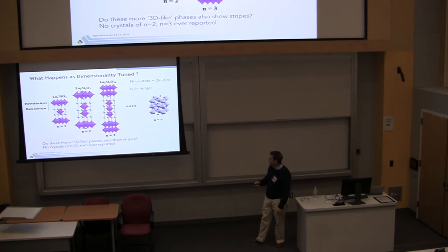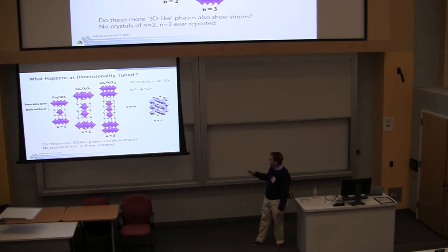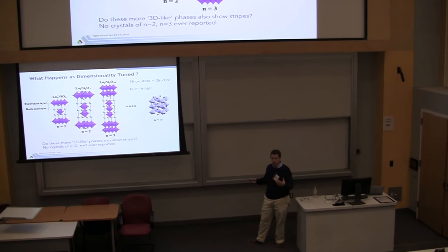but you don't find them when you go to N equals two or N equals three. So we said, well, maybe in the nickelates, the same thing will happen. But nobody ever grown crystals of these materials. And here's why. Here's a phase diagram. There's a lot of stuff on here. So let me just decorate it. So here's the N equals one material that people grew and did the Tranquada crystals. And they were float zone crystals, by the way. This material is stable at a very high temperature. It melts peritecticly, but you can grow the crystals.